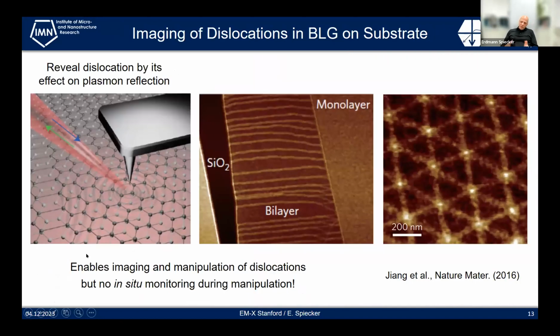I just want to mention that there are other means to image dislocation, and there's a very nice work by Jiang and co-workers who used a plasmon reflection to reveal dislocations on a bulk substrate. And they could also manipulate these dislocations, but it's of course not possible to image the dislocation while you manipulate them, but you can only do this afterwards. But it's a very nice technique to do that as well.